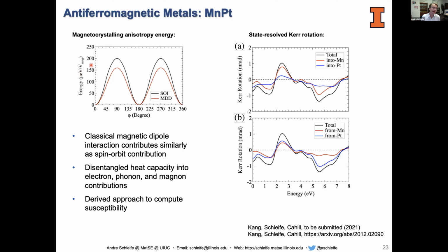But anyway, what we looked at in this material is, for instance, the magnetocrystalline anisotropy energy. So that's the energy that it takes to reorient the Néel vector in this material, simply because this barrier determines whether this material can be used efficiently for data storage, right? If you want to switch the Néel vector somehow, that may be a different question how you switch it experimentally, but if you want to switch it, the barrier cannot be too high. At the same time, if you want to store data, the barrier can also not be too low.